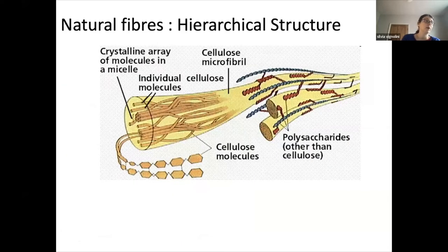When you look into natural fibers, the fibers you have are essentially cellulose fibers. And cellulose, again, has a hierarchical structure, because molecules of glucose form polymers, like strings of material. These strings entangle while they are biosynthesized with other cellulose polymers, forming fibrillar structures that, when they enter the plant cell wall, mix with other polysaccharides and lignin and create macrostructured fibers.